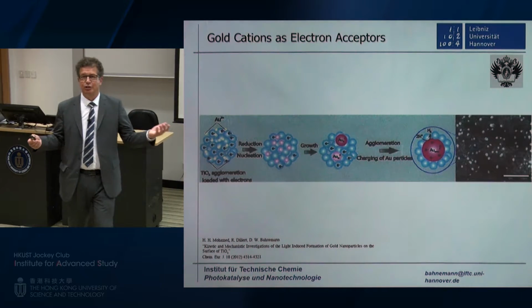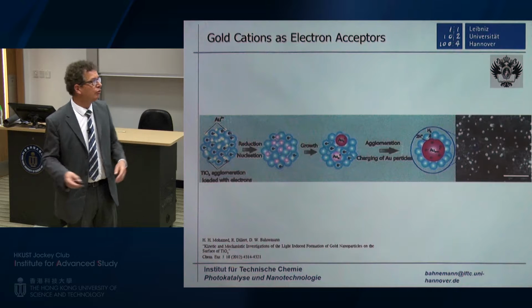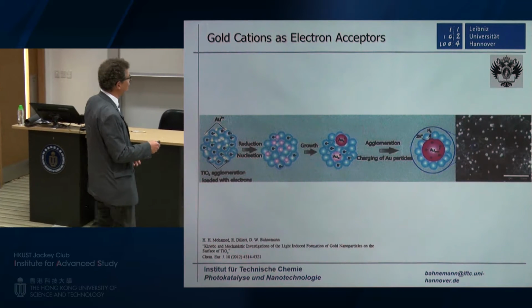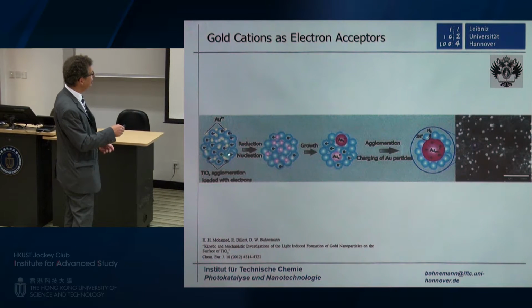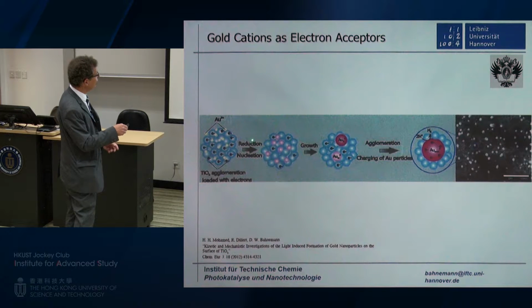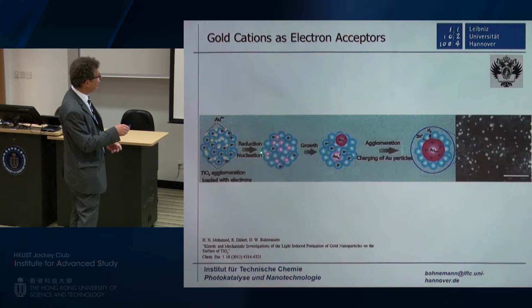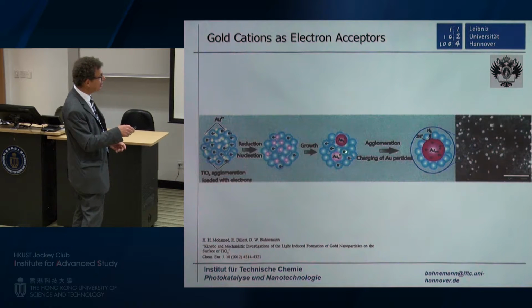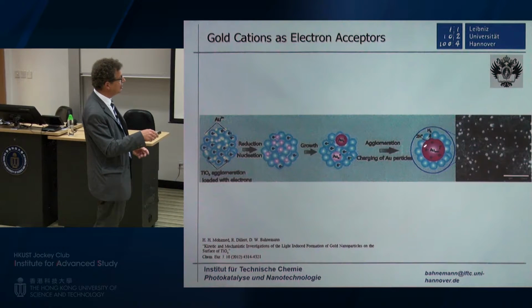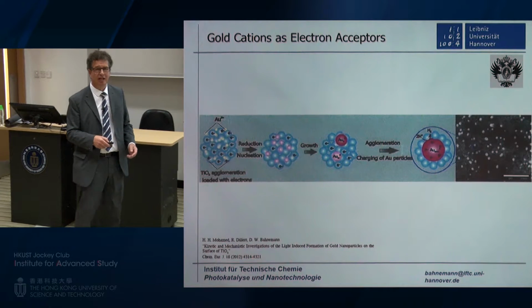Now you can change from silver to gold, for example, or to platinum or whatsoever, and you see the same thing. First reduction of the gold, nucleation, growth of the gold clusters until they become catalysts, and once they are catalysts, then you see the formation of hydrogen.